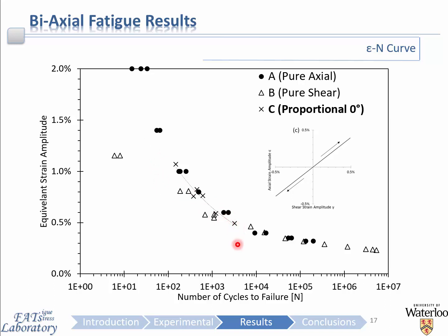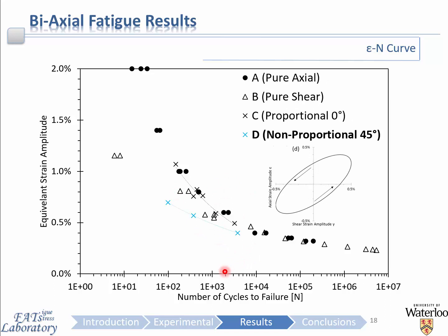Since there is no rotation of the principal axis here, the damage is accumulating along the same planes that were accessible of each of the uniaxial cases. However, what's quite interesting is when we look at the non-proportional data, a dramatic shift in the behavior can be observed, such that for a given strain amplitude, a lower number of lives is observed.